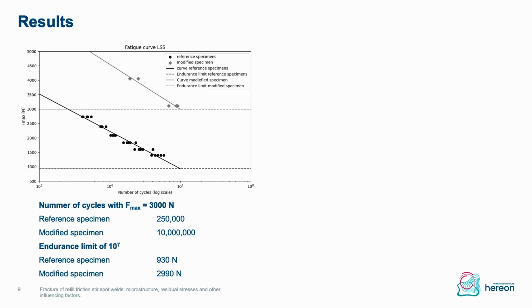On the left-hand side, you see the fatigue curve of a lap shear sample, where this is the Wohler curve of the reference specimen, and this is the Wohler curve of the modified specimen, where we're able to increase the number of cycles for a maximum load of 3,000 Newton from 250,000 up to 10 million, while the endurance limit for the reference specimen was 930 Newton, and in the modified sample almost 3,000 Newton.